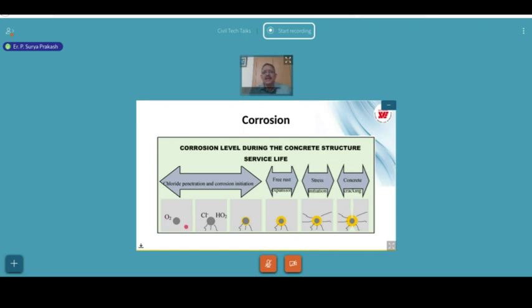So here, this is a diagrammatic thing. We have oxidation that happens to initiate corrosion in our crack. And then we have this onset of deterioration and the free rust. It opens up by the stage it comes here, and then it starts cracking. And then it will have the spalling and the full cracking at this stage, concrete level cracking and concrete spalling, it will happen. So this is the stage where we are. Oh, sorry, I should use the full screen. I'm sorry.